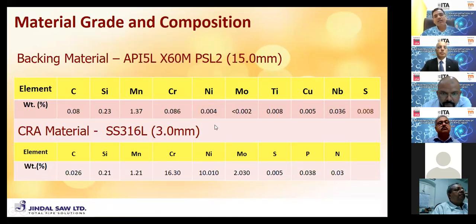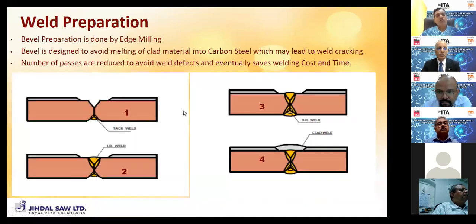So we have taken the base material as X60M of 15 millimeter, and the cladding layer was 316L of 3 millimeter. The chemistry of the 316L and X60M can be seen here. Next slide, please.